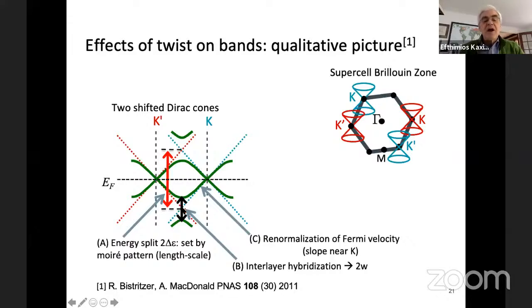And as I mentioned earlier, where bands intersect, they repel each other. So instead of the bands crossing each other here and here, they repel each other and form these new lines. So they open up these band gaps. So this is a very interesting, simple picture of trying to understand what happens when you put the two layers together. And this was put forward by Bistritzer and MacDonald back in 2011. And it captures the essential physics, but not in great detail.